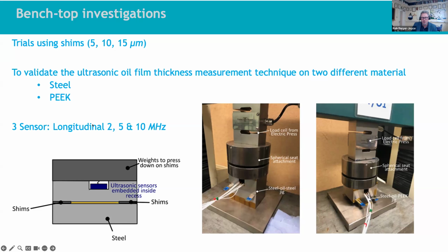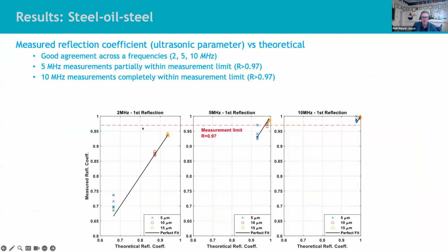One of the purposes of this experiment was to try out what different frequencies to use. The higher the frequency, the thinner the oil films you can measure. And what do we need for these actually relatively thick oil films? So we started out with steel, oil, steel against steel with an oil film in the middle. And these oil films are actually relatively thick in tribological terms, and so you want to have fairly low frequency, and at low frequencies these are our measured reflection coefficient against our theoretical reflection coefficient. When you get to higher frequencies, then more of it gets reflected back because it's not quite so sensitive, so it becomes harder to take the measurements.